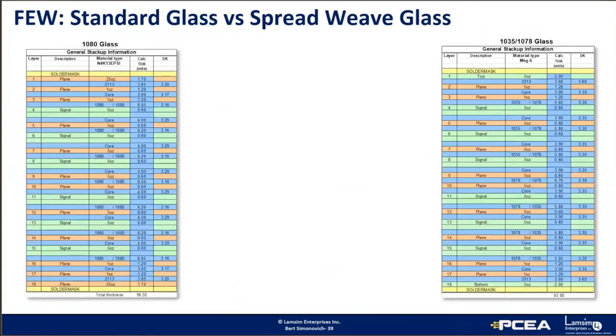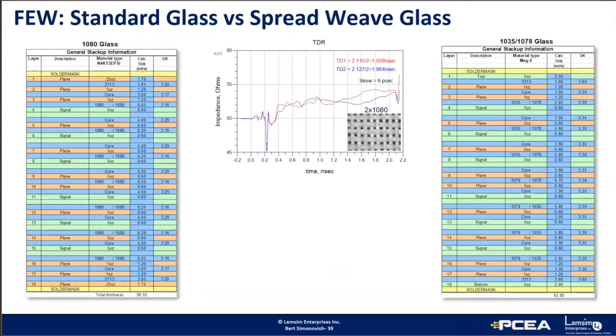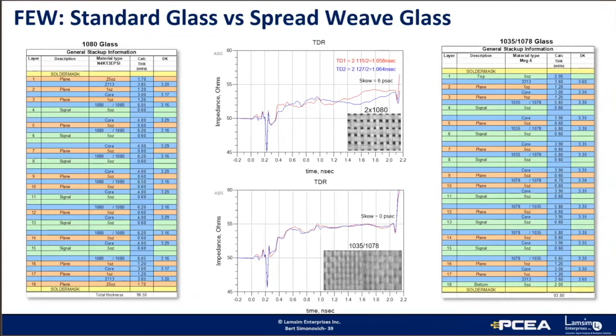So here's a real-world example of fiber weave effect skew. The same design was built using two different materials and glass styles. The one on the left is a stack up with Nelco 4000-13 EPSI using 1080 glass. On the right is a Meg 6 stack up, but with 1035-1078 spread weave glass. With the 1080 glass weave, we see variation of the impedance between the P and N and 6 picoseconds of skew. But with the 1035-1078 glass, the variation between P and N is similarly behaved, and there was no skew.